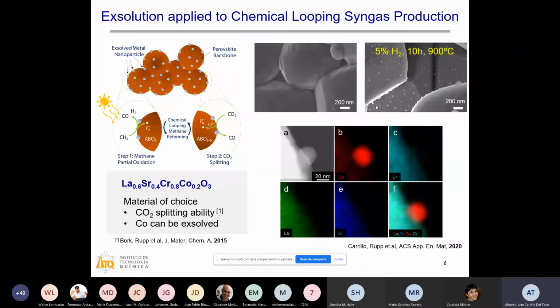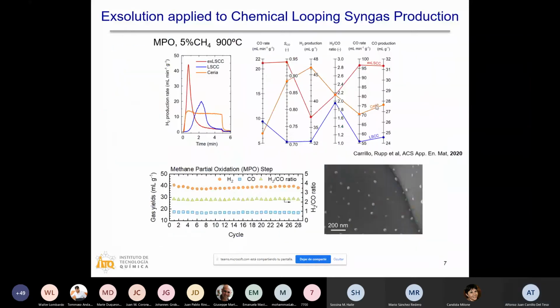And as we expected, the metallic nanoparticles are only composed of cobalt, as you can observe in these beautiful TEM images that were taken by my good friend Zachary Hood. So we carried out the reactions with these materials. On the top left, we saw the hydrogen production rate versus time for the exsolved material, the material without nanoparticles, and ceria as a reference. And we observed that the exsolved cobalt nanoparticles increase the kinetics for the material with respect to the bare perovskite.